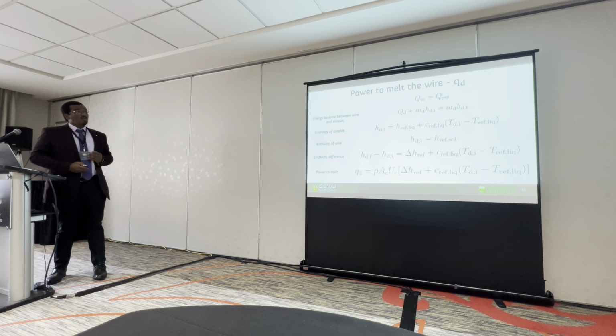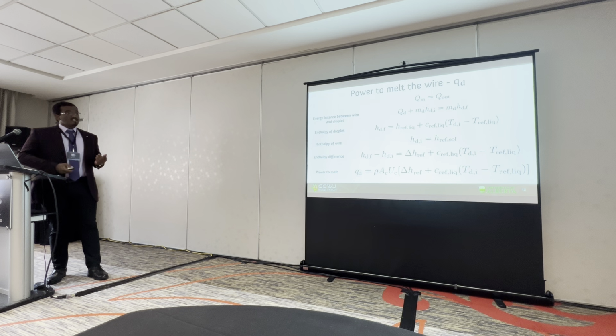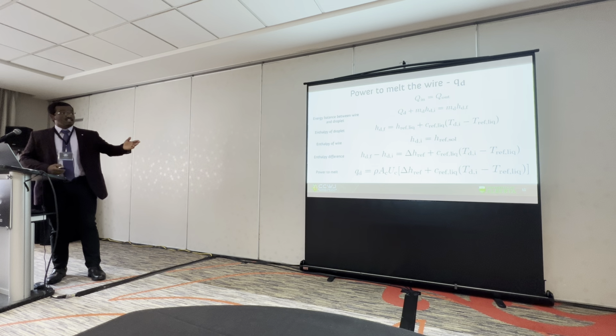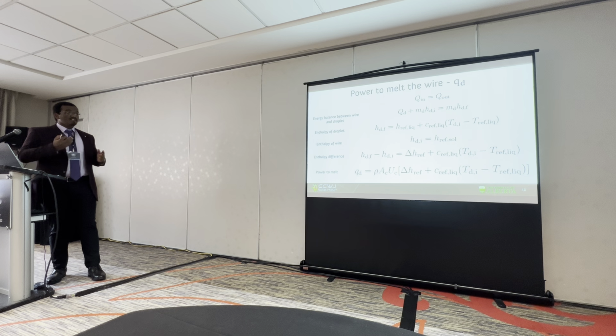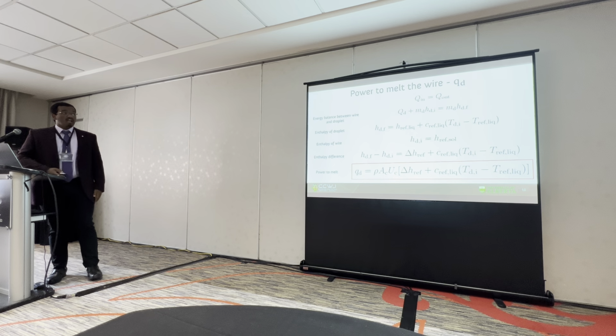So for this, we again do an energy balance from the initial stage, in which we have just a solid wire at room temperature T0, to the molten droplet, which is the final stage. Once we perform the energy balance, which is Q in equals Q out, we can say that QD is the power delivered to the wire to melt it from the initial stage to the final stage. Then we find the difference in enthalpy of the droplet and the enthalpy of the wire, and subtract it, and we are able to find the power necessary to melt the wire, QD. This QD is dependent on the density, the wire feed speed, the area of the consumable, and the droplet temperature.